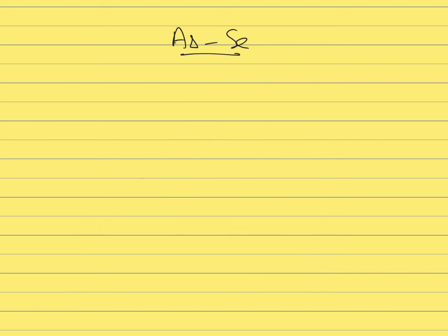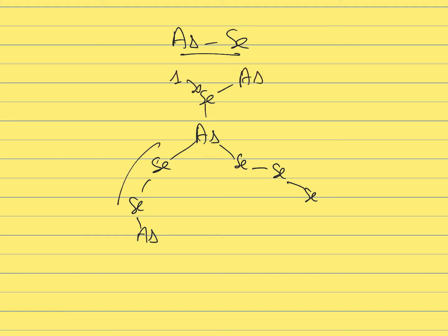Another common example of chalcogenide glasses would be an arsenic selenium glass. In that case, you have the arsenic atoms that are the cross-linking elements that are cross-linking some chains of selenium. So same thing, you have some chains of selenium. They don't have to all have the same size. Some of them can be short chains with a length of only 1. Some of them can have a length of 2. Some of them can have a length of 3, etc. So the size of the chain is fairly random in the structure, and it's going to depend on the composition of the glass.